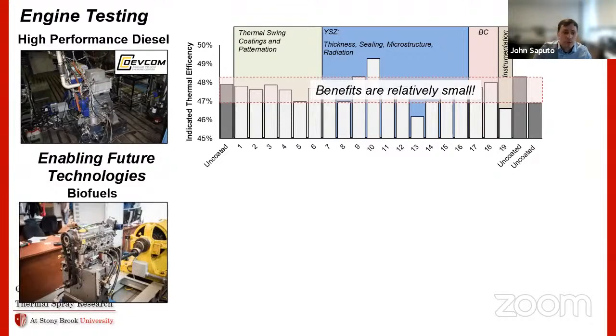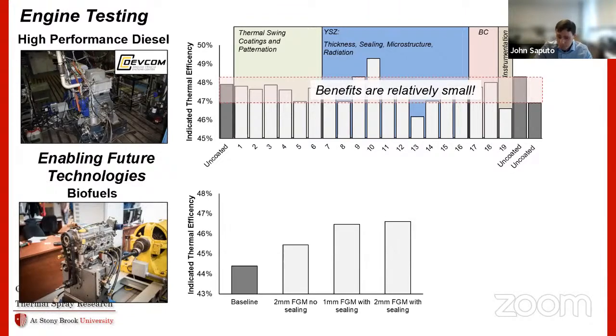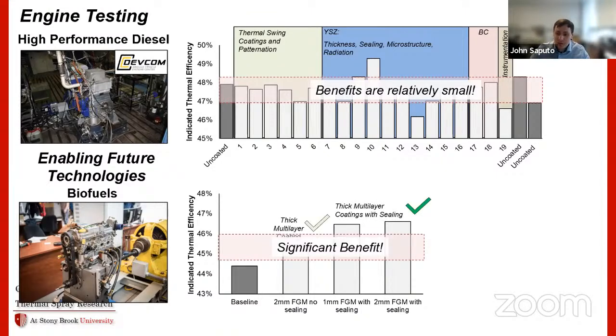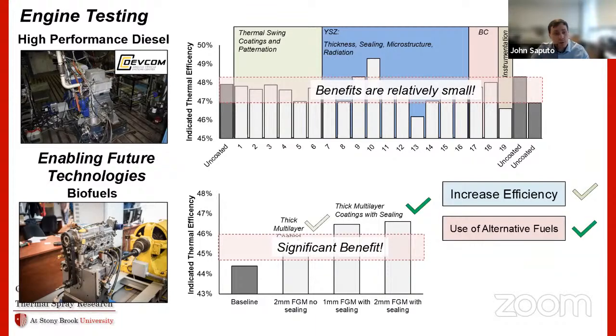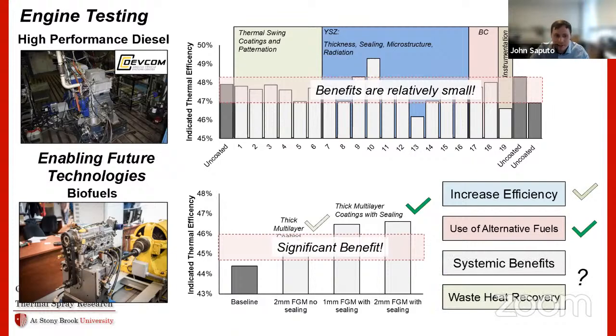One of those big things is biofuels. This is work that we did with Clemson, and it gets interesting. Use a lot of these same coatings and compare it to a baseline engine, and you immediately see the performance go up. In these systems where there are current limitations, the baseline engine performance is about 44.5%. For that high performance diesel engine, it was 48%. So you're already starting lower and there's more room to move upwards, which is kind of interesting, and you can immediately start gaining benefits from that. Which is great. So in these systems, there is a direct significant benefit that enables these biofuels, which have issues, to combust and perform like a more traditional engine. So increased efficiency directly, kind of questionable. Use of alternative fuels, absolutely. Systemic benefits and waste heat recovery, kind of questionable.